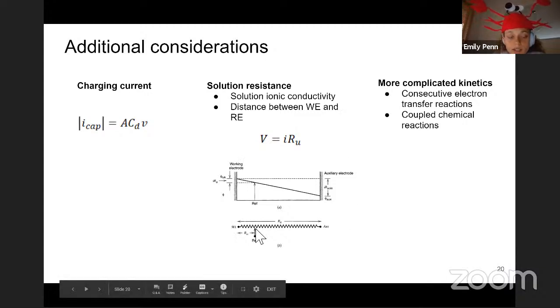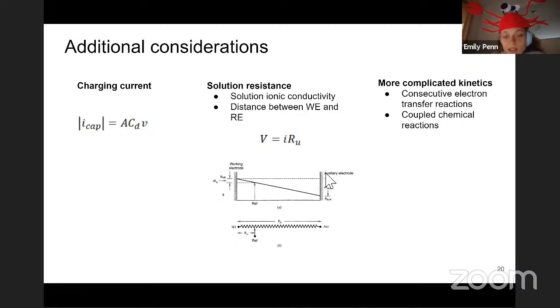In this figure, we can see that the working electrode is at some potential, and your auxiliary or counter electrode is at some other potential, and this IR drop is due to the solution resistance. But the potential that you're measuring at the working electrode is the potential between the working electrode and the reference electrode. So this potential drop here is an uncompensated resistance. If you are able to move your reference electrode closer to your working electrode, then you're able to reduce this uncompensated resistance that might distort your voltammogram.